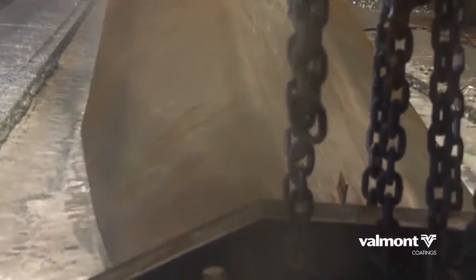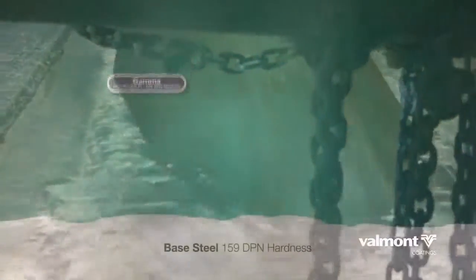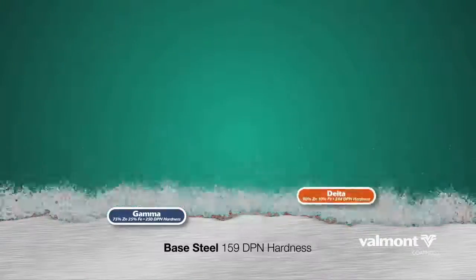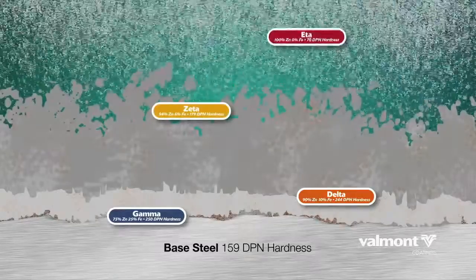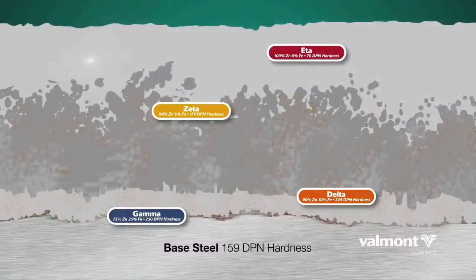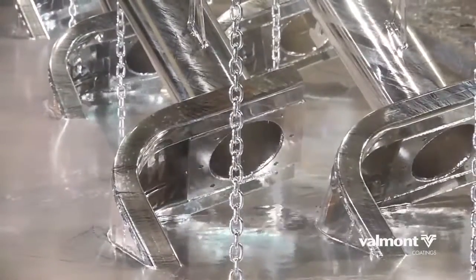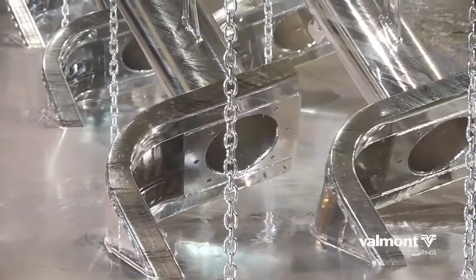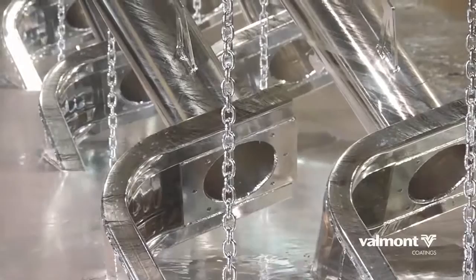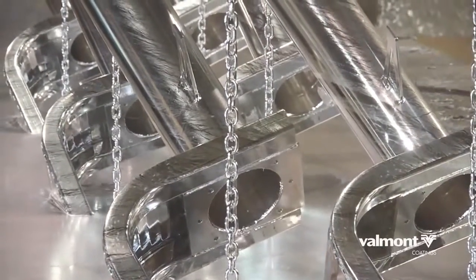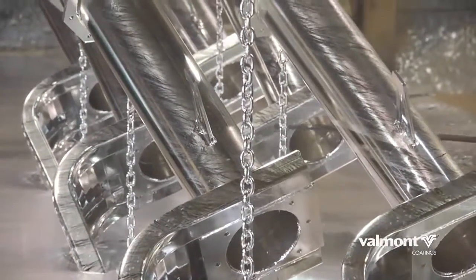In the field of metallurgy, zinc has a special relationship with steel. In the bonding process called hot-dip galvanizing, the zinc chemically bonds with the steel to form a series of zinc-iron alloy layers. The final layer is 100% zinc. These tightly adhered layers become extremely abrasion resistant because the intermetallic layers are harder than the base steel. So the protective zinc coating actually becomes harder than and part of the steel used in the structure.